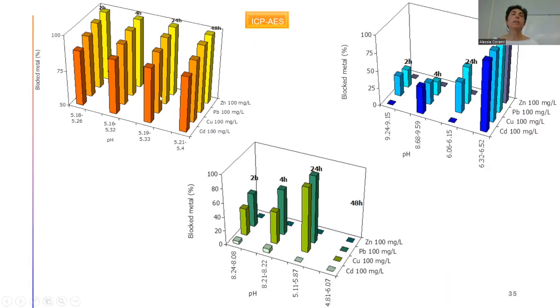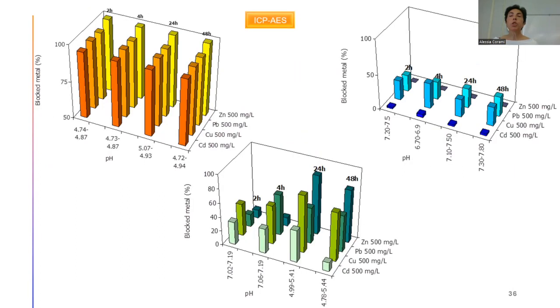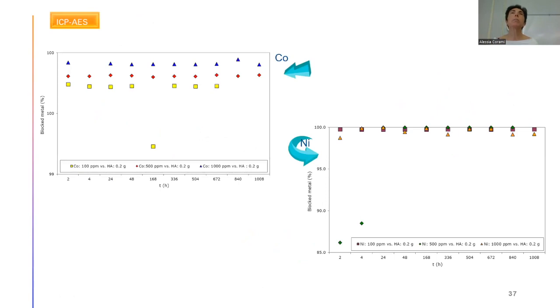Then we plotted together the amount of metals that could be immobilized with the pH. In this case, we have a concentration for the metals of about 100 ppm. This is for the synthetic hydroxyapatite. They are well immobilized, it doesn't matter the time. Here we have the US apatite, and after 48 hours, metals could be well immobilized. This is the Moroccan phosphate, and 24 hours is the suitable time. But if we change the concentration, we observed that the US apatite, fluorapatite, is not as good as before, but the Moroccan phosphate is better. After 24 hours, we have a good immobilization of metals. And then we analyzed this phosphate for the immobilization of cobalt and nickel.